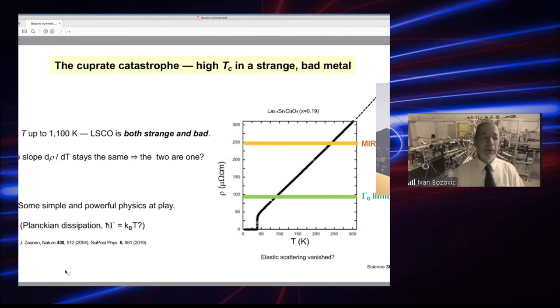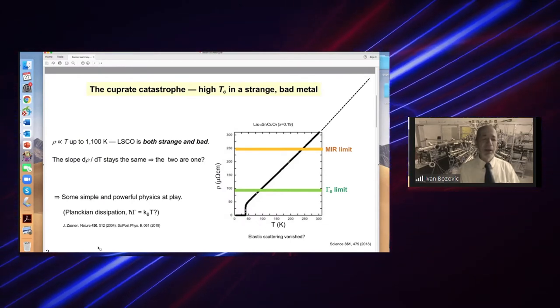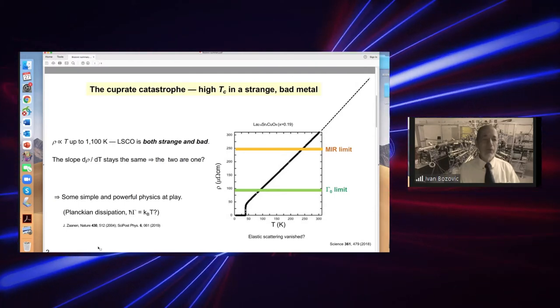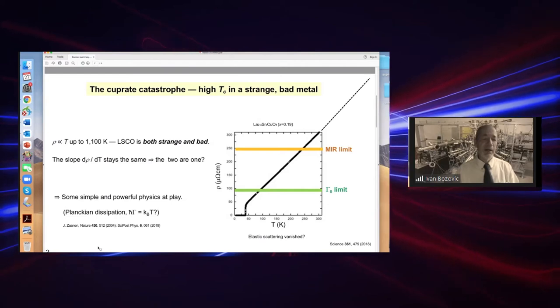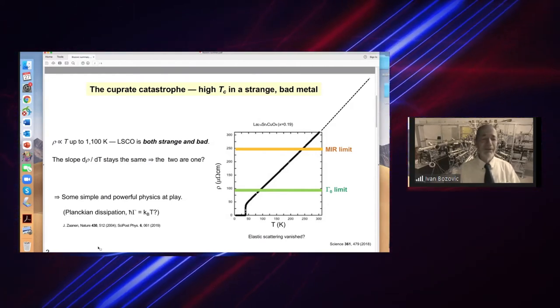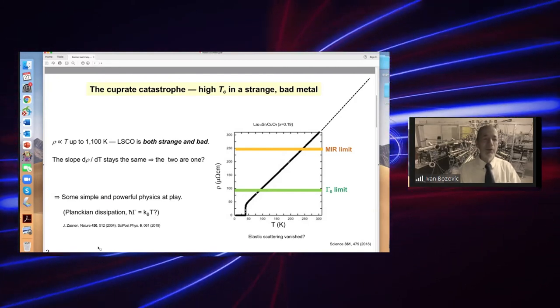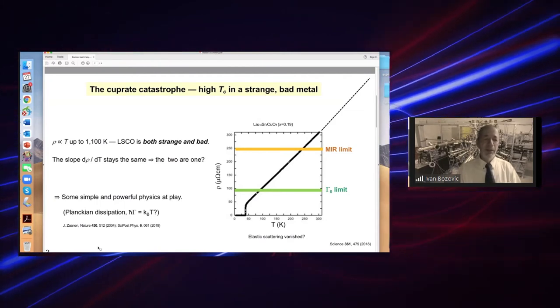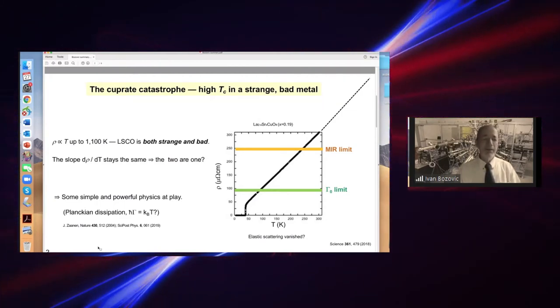This is currently a very hot topic, going under the name of bad metals, meaning metals that violate the Mott-Ioffe-Regel limit, or strange metals, meaning that resistivity remains linear down to millikelvin temperature, and in some cases, the elastic scattering seems to be completely absent. And in cuprates, both of these can happen, and sometimes both in the same sample, the same material. And in the case of LSCO, the slope actually stays exactly the same, from Tc all the way to above 1,000 kelvin. And that points to the fact that both the bad and strange metal behaviors may actually be of one and the same origin.